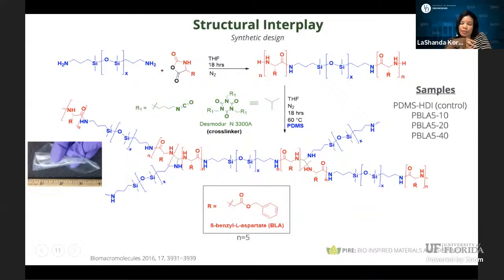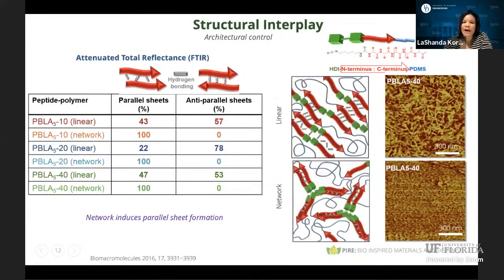Nicely, you see in the picture on the left, we're able to make really nice and flexible transparent films. Here we're sticking to beta sheet structure. So PBLA has a block length of 5, and we're controlling the composition 10, 20, and 40. I'll remind you a bit about thinking about this parallel versus anti-parallel beta sheet structure. So for our linear systems, as we anticipate, you're able to control the anti-parallel content as you increase the composition. But you'll notice that for the network systems, no matter the composition, 10, 20, or 40, you only have parallel sheets, parallel beta sheets. And these parallel beta sheets are not the most thermodynamically stable structure.